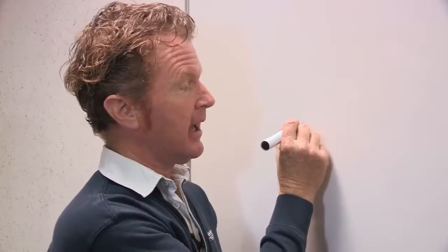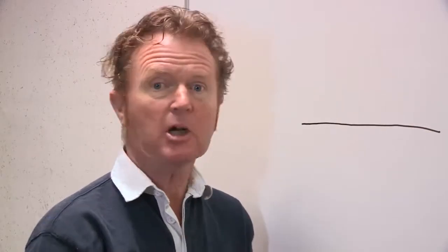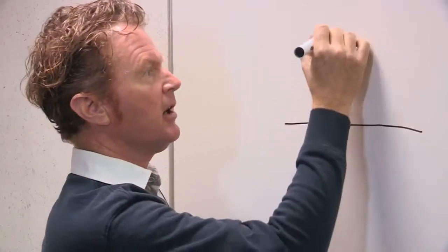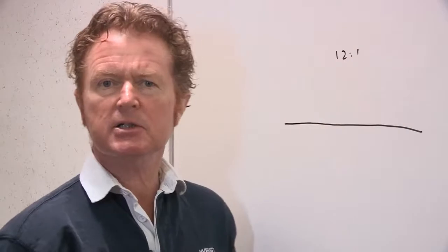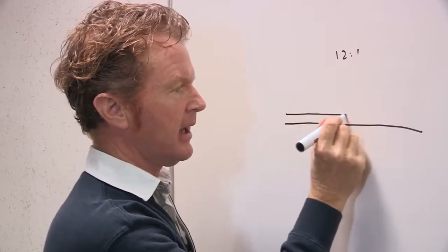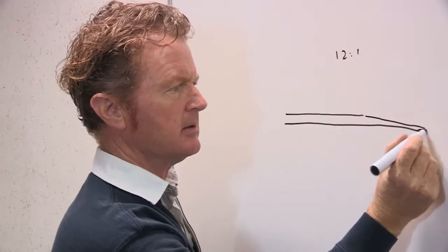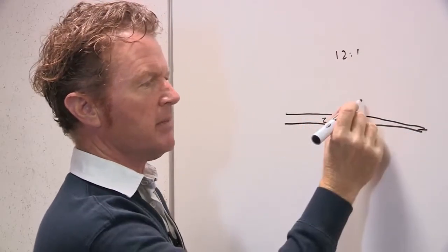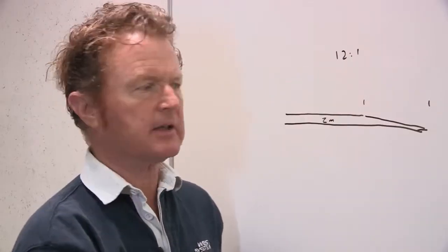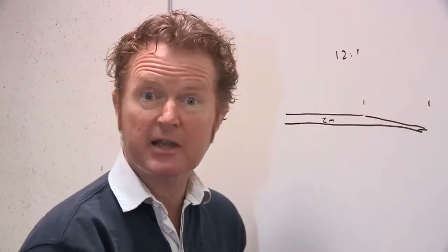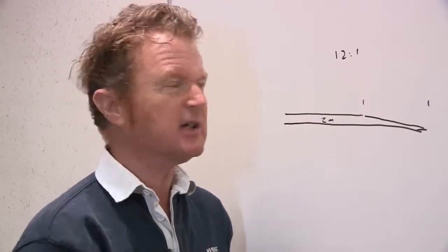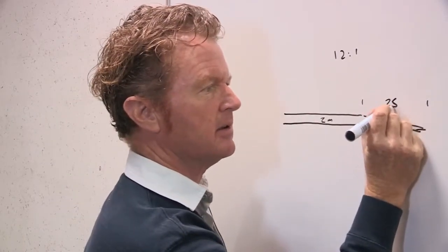So knowing our laminate thickness from our measurement with our calipers, we can now look at preparing the repair. And we work on a very simple formula of creating a taper or a bevel or a scarf joint to enhance the contact surface of our new laminate. We work on a 12:1 taper. Now, given our laminate thickness is 2 millimeters, we want to make a taper that is 12 times that thickness. And that equates to, if my maths is correct, 24 millimeters, but we'll just make that 25 millimeters to round the number up.